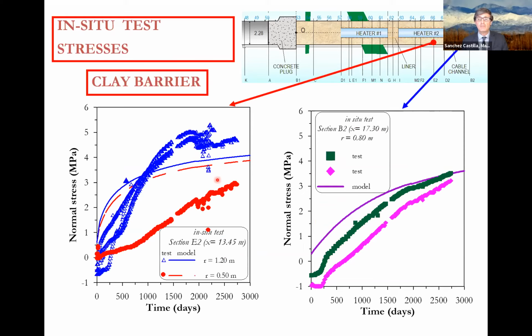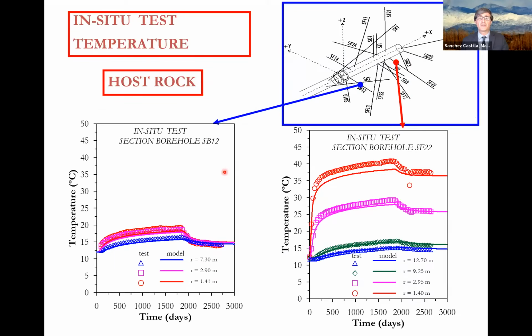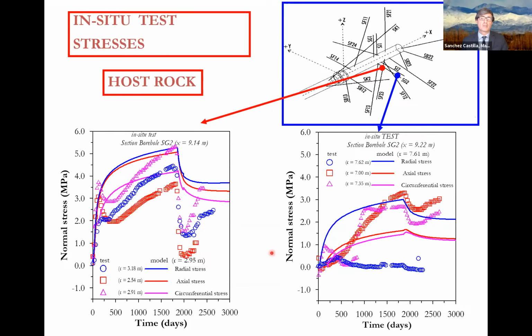This is all the result in terms of stresses. In this case, you can see that we have quite a high increase of stresses, up to 5 megapascals at the end of the experiment. Also, what happened in the rock around the experiment in terms of temperature: in the borehole closer to the heater, we have the higher temperature we expect, but as we move away from the heater, the temperature is lower. This decrease that you observe here is related to the cooling down after the switch off of heater one. These are again results in terms of stresses, and again they show that the model managed to predict the evolution of the system very well.